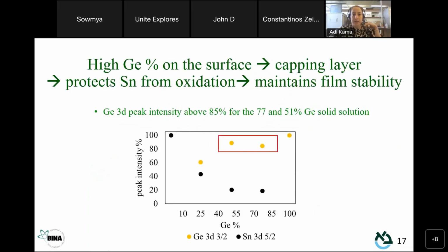Also from the XPS, we noticed that the germanium peaks have very high intensity, even though the concentration is decreasing. And we found that we have high concentration of germanium on the surface of those materials. The thin films have a high concentration of germanium on top that we assume protects the film from further oxidation.